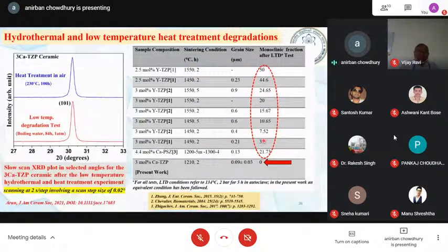How much have we got? Zero. And again, I believe the beauty is here. None of them are controlling the grain size below 100 nanometers. When you control the size, you can achieve a lot of properties, which is phase stability of tetragonal here. Size is controlling the phase transformation.